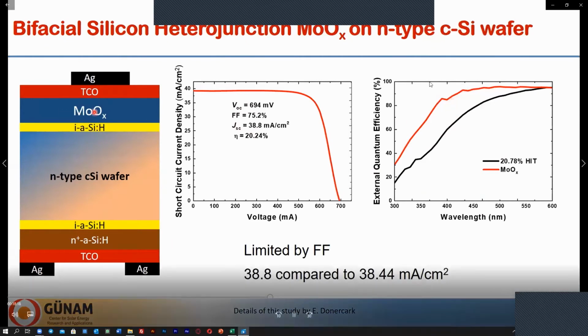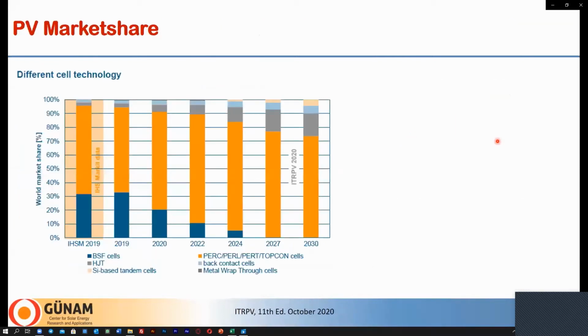So we have higher JSC, we have higher blue response when we have molybdenum oxide, because molybdenum oxide has a higher band gap compared to the amorphous silicon hole collecting layer in the standard heterojunction solar cell. However, on the other hand, according to the International Technology Roadmap for Photovoltaics, which was published a few weeks ago, it was found that